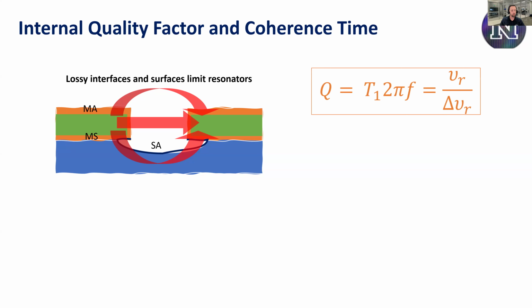So the simplest way to look at this loss is through the measurement of what's called the quality factor. The quality factor is proportional, more or less, to coherence time, which is ultimately the figure of merit that we really care about. Resonators are much easier to make, simple meandered structures. So a lot of the materials type work is really done at the resonator level. This quality factor, just the sharpness of your resonator's peak, depends on the design, QC, but also on the internal quality factor, which is really the part that's due to materials loss. So as material scientists, that's the part that is kind of our responsibility in a sense.